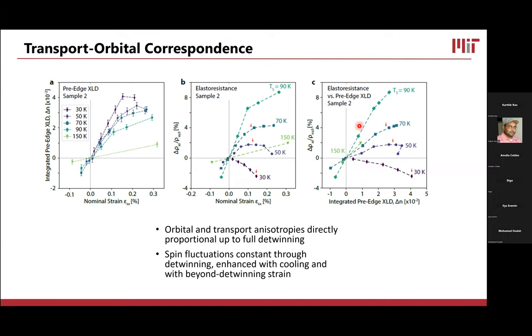So in this strain range, basically, we're not making changes to the lattice constants. But as a function of temperature, the resistivity anisotropy is dropping. So if we're thinking about a single domain, we're going to have some orbital polarization in it, and we're going to have some spontaneous value of the spin fluctuations. And presumably, both contribute to the elastoresistivity. As long as I'm only detwinning the sample, I shouldn't see a change in the orbital polarization or in the spin fluctuation spectra. So my resistivity should stay linear to strain because it's basically just following the detwinning.